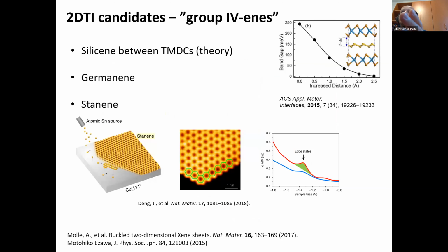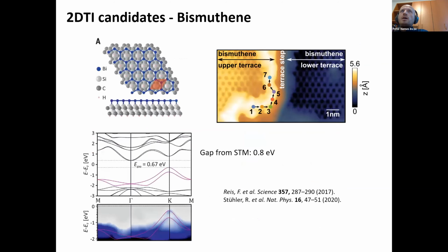And indeed, I'm showing here an example of stanene. This has been produced using molecular beam epitaxy, and people have shown with STM that indeed this material hosts edge states. Another prominent example, and possibly the largest band gap material that you can get, is a monolayer or a 111 bilayer of bismuth, which should have a band gap in the hundreds of milli-electron volts, so well above room temperature.